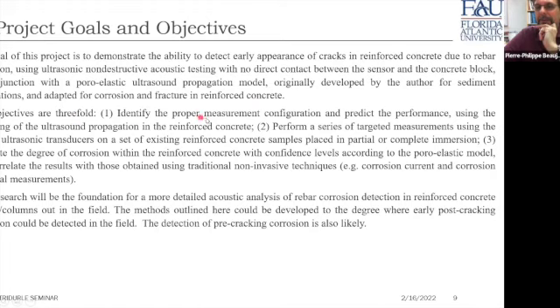Number one, to identify the proper measurement configuration and predict the performance using the modeling of ultrasound propagation in the reinforced concrete. Two, to perform a series of targeted measurements using the proper ultrasonic transducers on a set of existing reinforced concrete samples placed in partial or complete immersion. And three, to evaluate the degree of corrosion within the reinforced concrete with confidence level according to the poro-elastic model, and correlate this result with those obtained with traditional non-invasive techniques, such as corrosion current and corrosion potential measurements.